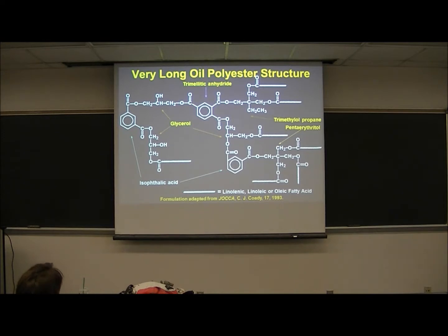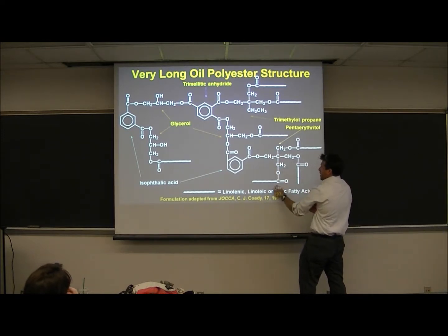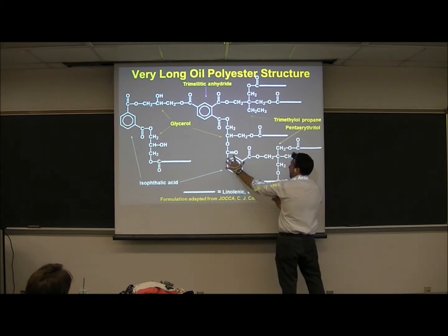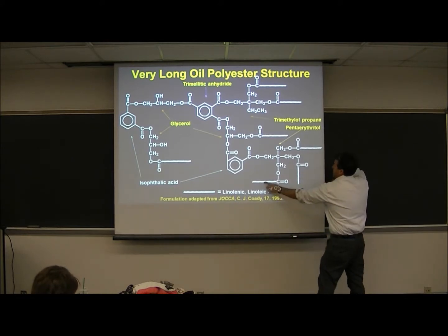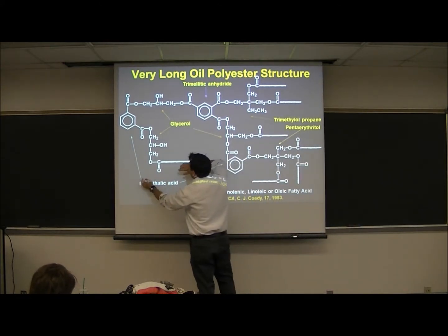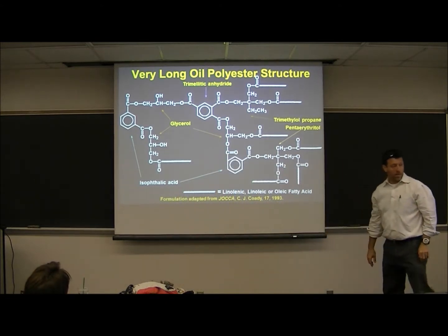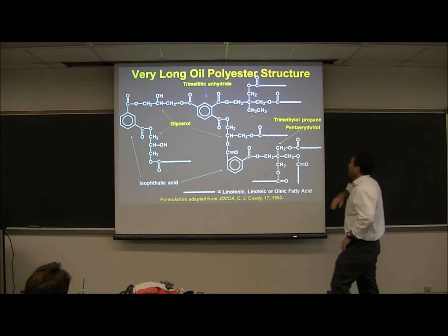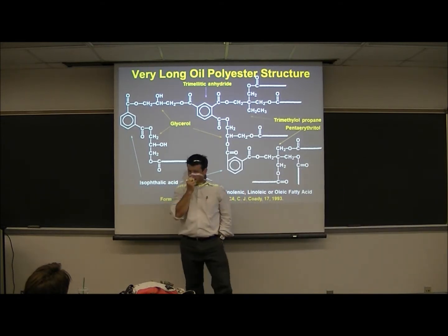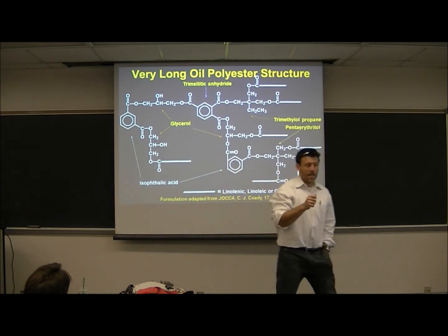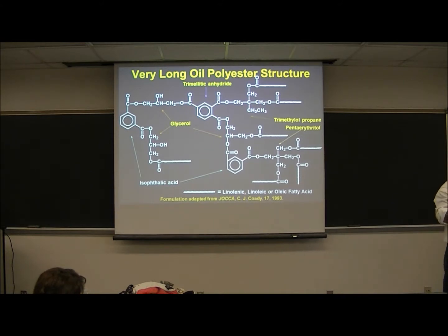And you see where here's the pentaerythritol, the tetrafunctional alcohol residue. Here's the isophthalic acid. Here's the fatty acids all over the page, giving you the acid or the oil length. And then, of course, here's TMP. Here's glycerol. I don't know if you caught it on the one slide, it actually says we want about 10% excess hydroxyls. And you want that. It's another method of keeping it from gelling.